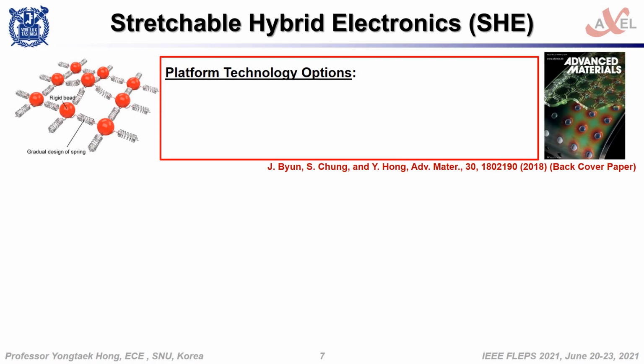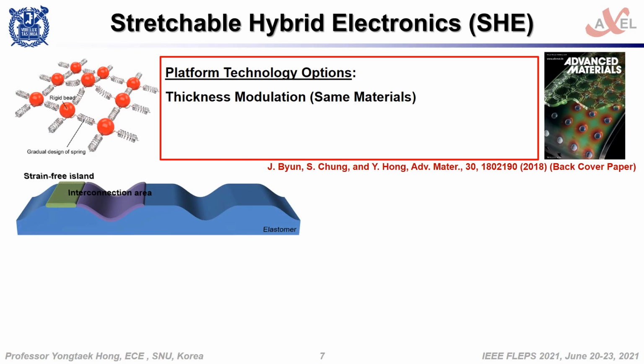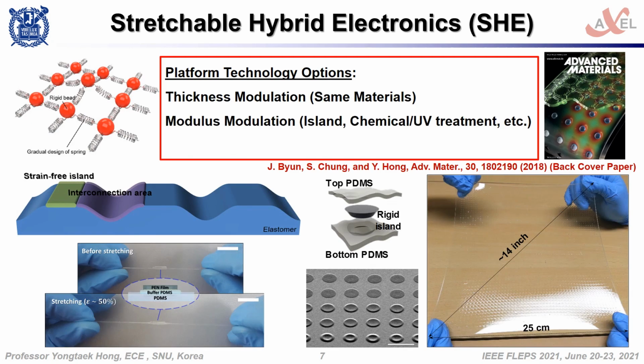In order to engineer strain for stretchable platform, thickness modulation for the same materials, and modulus modulation using hybrid materials or chemical UV treatment methods are being used. It is very important to have scaling up and easy fabrication features. In both approaches, handling of highly localized strain is a key issue for stably operating stretchable electronic system.